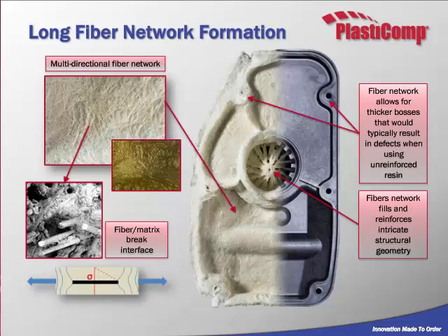So on that part, I also want to point out that the bosses are thicker than normally recommended by typical plastic design standards. Normally that's frowned upon because you're going to get a lot of shrink and a lot of warp, but this is where fiber filling your part really helps you out. Because it doesn't have as much shrink, you're not going to have that issue, and you can feel free to have a thicker boss. You also see that molded-in intricacy that Eric spoke about earlier. We can still fill those fine sections with long fiber.